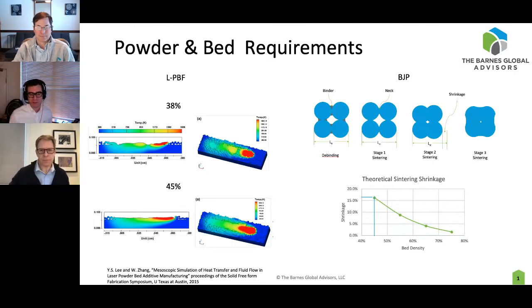And so having considerations for the feedstock and how the particles interact with each other, how you then put them into the machine, how the machine is going to behave, and how all those factors result in a functional piece of hardware at the end of the day is far more complicated and different between the two. We see that with the theoretical sintering shrinkage, basically how dense can you get your powder. But then you have to ask how you get your powder in the powder bed space and be that dense. There are a bunch of mechanistic problems to overcome to get powder to behave the way you want to optimize binder jetting, versus different constraints on the powder bed fusion space.